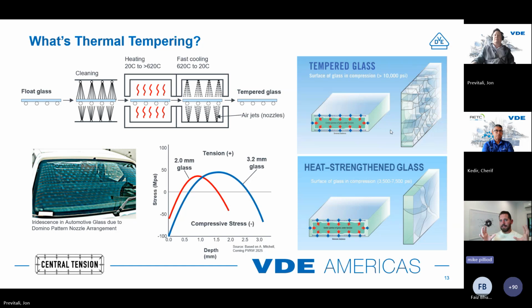The reason I mentioned that is that you need a stress balance within the glass. If you continue to put too much compressive stress on your surface, you can get into the frangibility limit. So if you hit the corner of the glass, the whole thing shatters like crazy versus having a single line crack or a low stress crack. You can over strengthen glass in a sense. Doing a thermal tempering like that is kind of tough because you end up breaking it in the tempering process. But that's kind of the area.